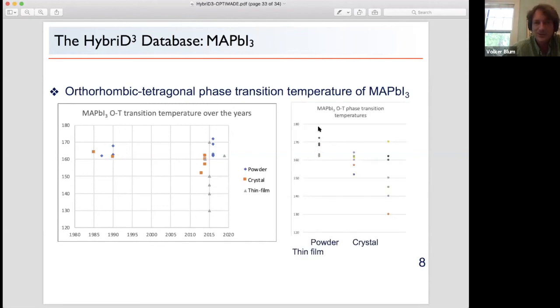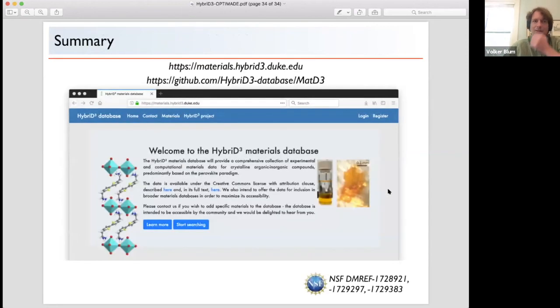And so we can actually see that the powder data occupy the highest range of the phase transition temperatures measured. The powder, the single crystal is here. This got moved. Apologize. I don't know why the axis label switched lines. It should not have, but it did. But anyway, this is powder, this is single crystal, this is thin film. And so we can extract data like this. And this is already the summary of what I wanted to say. There's more data, of course, and we're trying to grow this, but my main interest is also in the discussions.